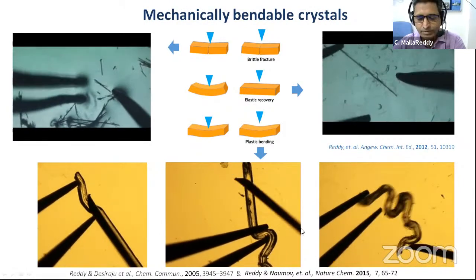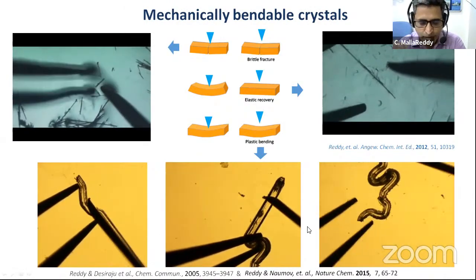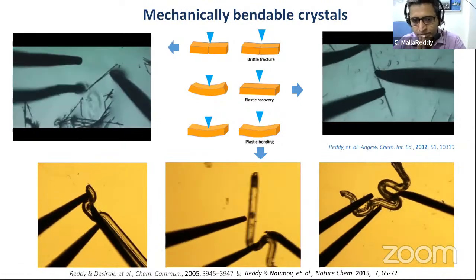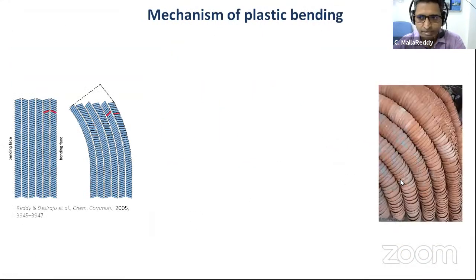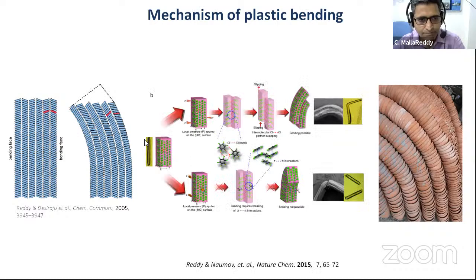So then again, we try to understand whether the model that we proposed, the slip plane model, was right or not, using some advanced techniques. I'm not going into the details again. So this was the mechanism that we proposed for the plastically bendable crystals. You have weak interaction planes, and then you have stacks of molecules. So then because of this slip, you have the bending.